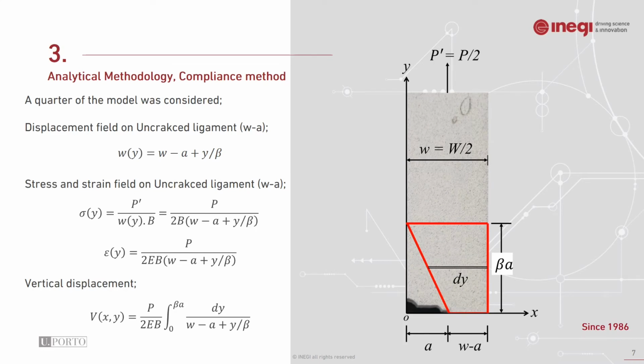So the equation is going to be presented here. So just a quarter of the model is going to be considered. In this case, P prime is the applied load divided by 2, and the small w is the total width divided by 2, and a is the crack length and the uncracked ligament is W minus a. It is possible to obtain the displacement field and afterwards the strain and stress field on the uncracked ligament. And finally, it is possible to obtain the vertical displacement by the integration of v(x,y) equal to P over 2EB integrated from 0 to beta a of dy over (W minus a plus y over beta). This is the vertical displacement.